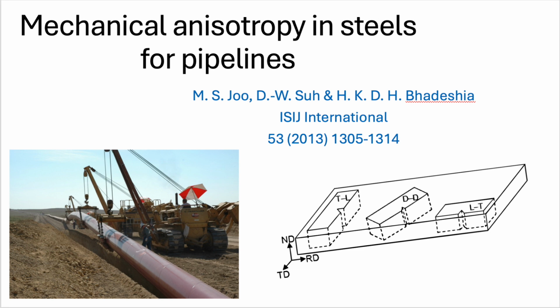Precisely. And anisotropy messes with this whole picture. It means the energy values, both ductile and brittle, depend on the orientation of the test sample relative to how the steel was made. Which is a nightmare if the direction facing the highest stress happens to be the weakest one. That's the core risk. So we need to understand why this happens. The source material we looked at highlights three main culprits for this toughness anisotropy in hot-rolled pipeline steels. Okay, let's break them down.